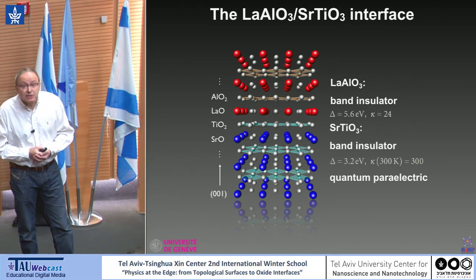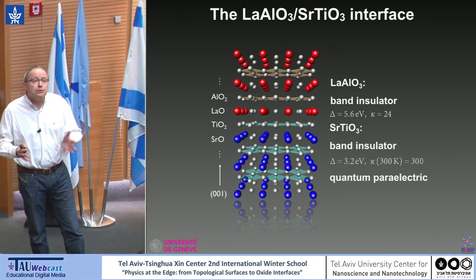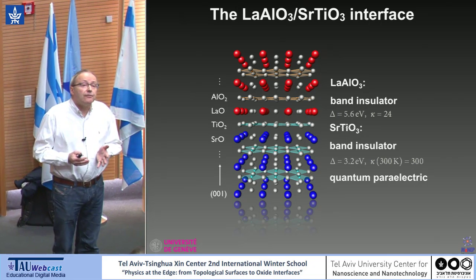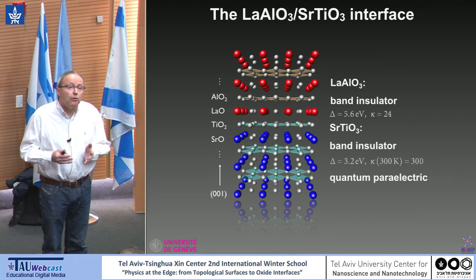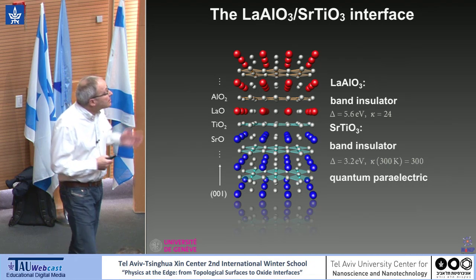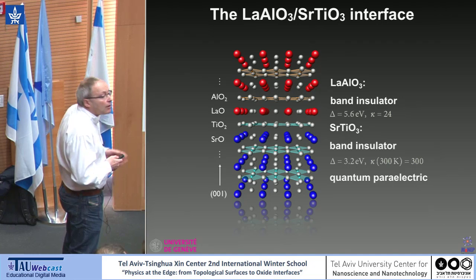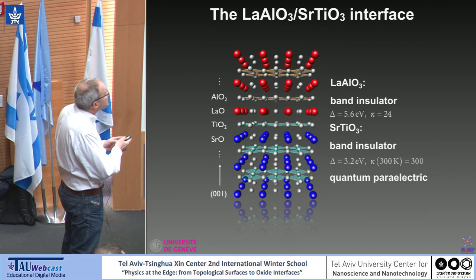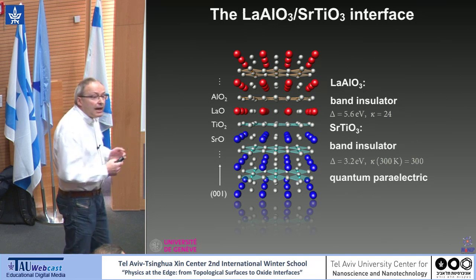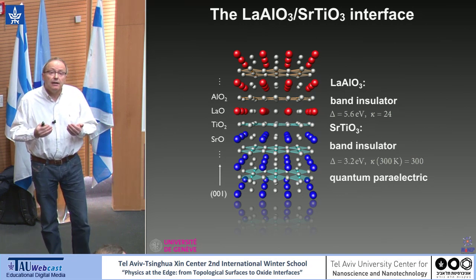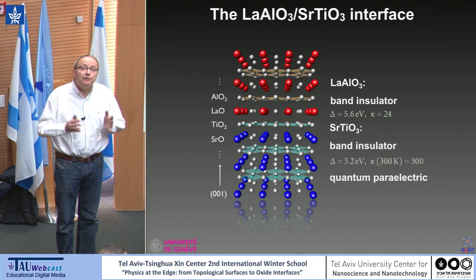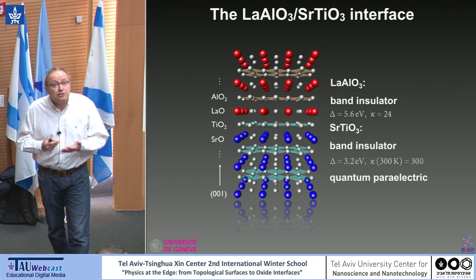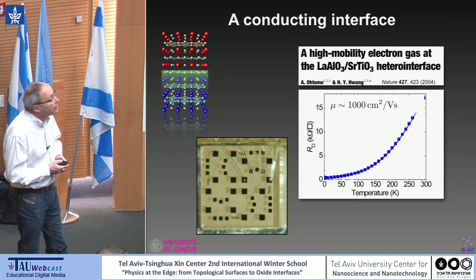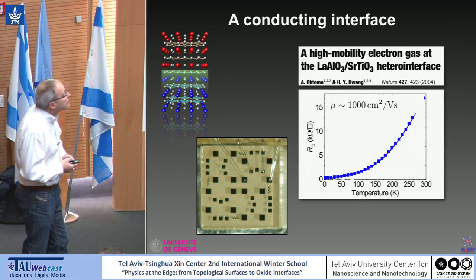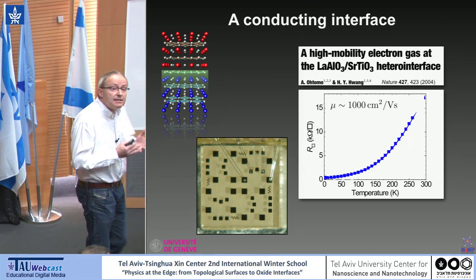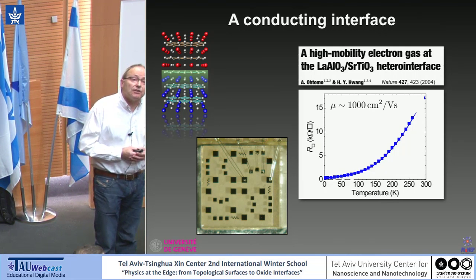And it was found in 2004 that if you start with a single crystal of strontium titanate in the 001 direction, and if the single crystal is terminated by a plane of titanium dioxide, which you see here, and you grow on this single crystal an epitaxial layer of lanthanum aluminate, you find at the interface between these two good insulators a conducting layer. And you see here the sheet resistance versus temperature. This system is metallic and has a large mobility.